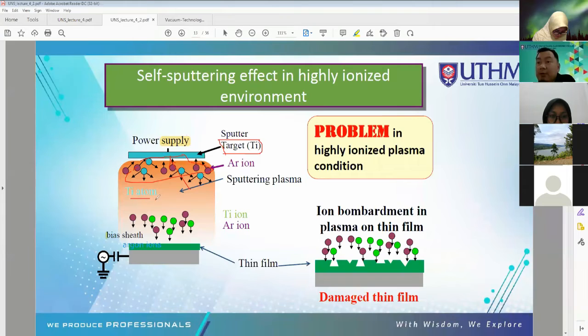In some cases, we not only have titanium atoms, we can also have titanium ions. Sometimes this is not good, because on the other side we try to create the thin film, where the atoms released here go to the substrate and create a thin film. This thin film sometimes gets damaged because of ion bombardment. Even though we want to do the sputtering process on the top, because of the bias of ions at the bottom here, this kind of ion will damage the thin film through the ion bombardment process. That's why we have to study how this phenomenon occurs at the bottom here.